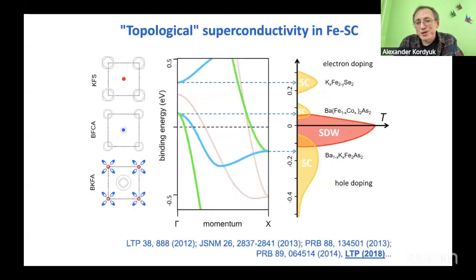This is also a different story, but when we go back to cuprates, I should admit that the model which we suggested about spin fluctuations may not be complete, because here it is difficult to calculate theoretically, because of the so-called vertex correction due to strong interaction, and you should anyway introduce some parameters by hand. You could not make it from first principle calculations. But based on the same structure, you could predict the critical temperature in quite a range. But it seems that in cuprates the situation is similar.